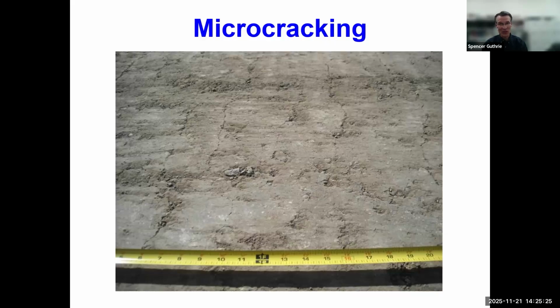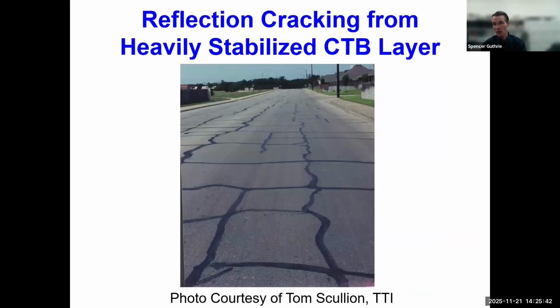But remember, the cement is not finished curing, and it will continue providing strength gain, such that by the end of 7 days, we normally see a complete restoration of the original strength, and it will continue gaining strength after that. So that's the microcracking procedure, and this is what you get if you don't microcrack.